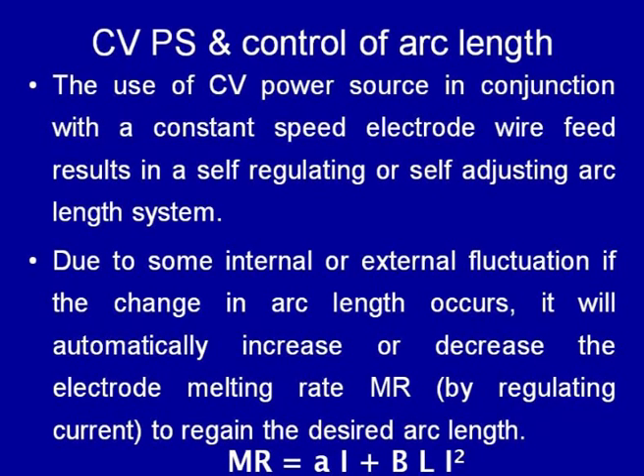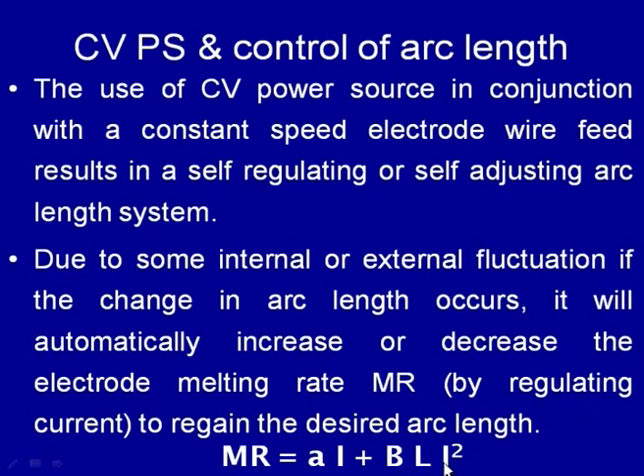And we know that under these conditions, when there is any fluctuation in arc length due to any reason, this causes a change in the arc voltage, and the change in arc voltage causes a significant change in melting rate by regulating the welding current in order to achieve the desired arc length. So, this melting rate, we know, is regulated by the AI plus BLI square. So, for small diameter electrodes having a large electrode extension and high resistivity, the second factor governing the melting rate is significantly influenced by the welding current. So, if the welding current is increased in a big way, then it regulates the melting rate significantly.